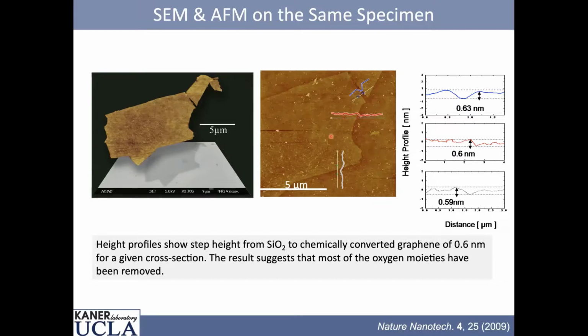Well, it turns out that we did this experiment on silicon, and the silicon is not a perfectly smooth surface. So we probably should go back and redo this on freshly cleaved mica, but it's hard to convince your students to go back and do that. But anyway, I just wanted to show you, this is one way of showing that we have single layers. Of course, there's many others. There's Raman and so on.